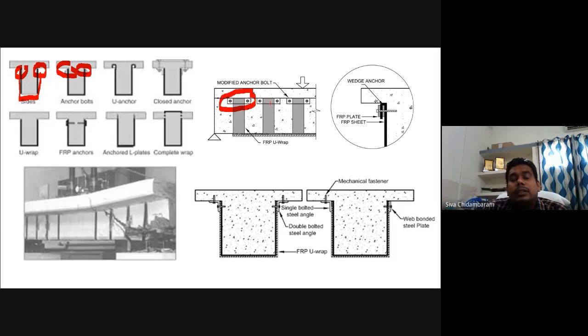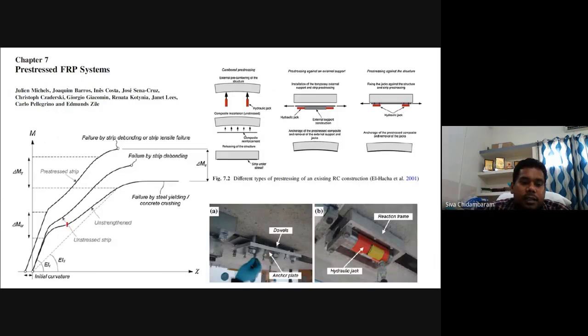When you are anchoring like this, it will not allow the FRP to delaminate, number one. So for example, this is called unstrengthened. This is strengthened, so the strength is increased, but delamination occurred. When you are using external anchorage, it becomes like this. Similarly, when it comes to pre-stressed FRP, the same can be attained. So this is for pre-stressed FRP. When you are using FRP with external anchorage, this will go like this. So you can increase the efficiency further.